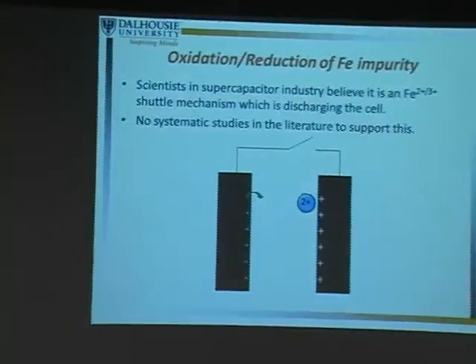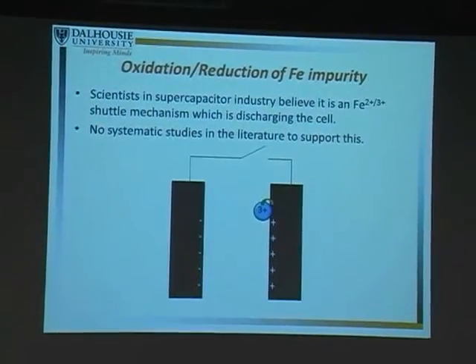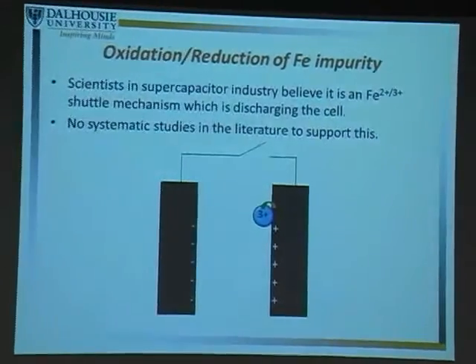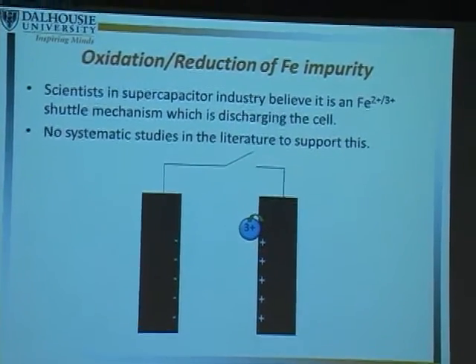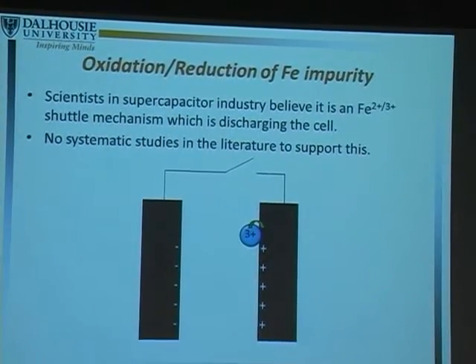And so what industry thought was happening, and what we thought was happening, is that in the sulfuric acid we would have a little bit of an iron contamination. I've just picked iron 3 here, but it's likely both. And then that iron would move over to the negative electrode, and it would essentially take an electron off that negative electrode. It would be reduced to iron 2, would then move over to the positive electrode, give up an electron, discharging both of the electrodes, and would shuttle back and forth.